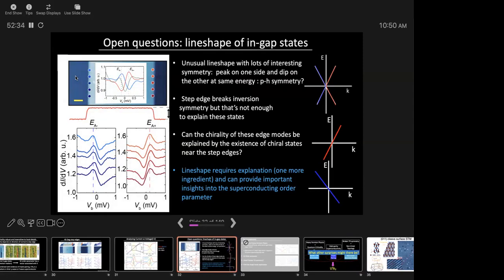First, the only way we could think of getting this line shape: if you have these kinds of linearly dispersing states living on your surface, and you break inversion symmetry, then you would get particle-hole symmetric features. You would either see this thing or this thing on the step edges, with states above and below the Fermi energy, a flat density of states. The only way we could think of explaining this is to imagine that there is a chiral state living on this sample. And then when you go to the edge, you preferentially tunnel into one momentum or the other. That way you would pick up all of these states and not these on one step edge, and all of these and not these on the other step edge. That would not happen if you had helical states. That could only happen if you had chiral states. Kind of a Doppler shift.